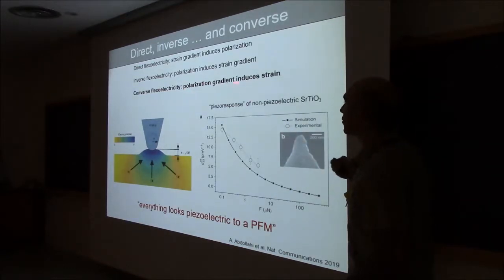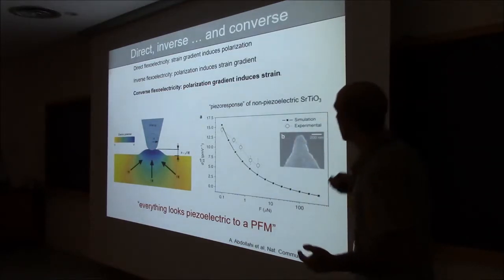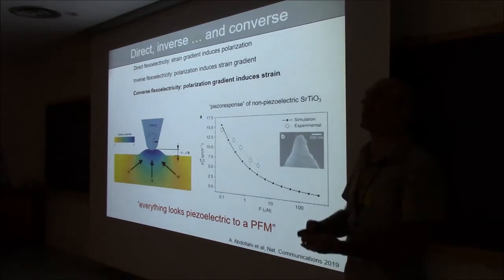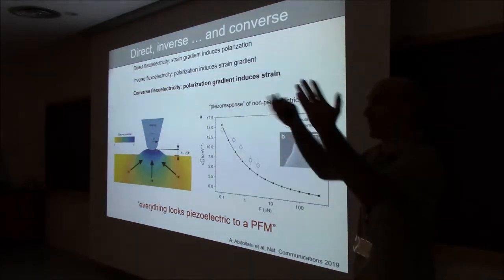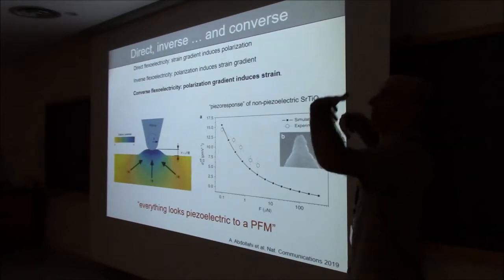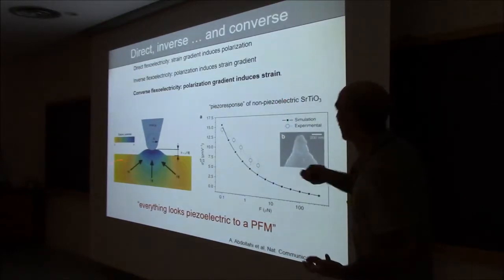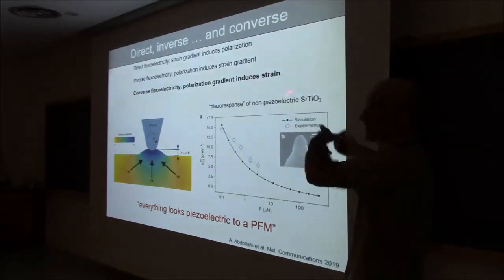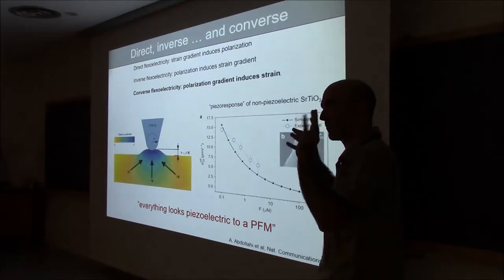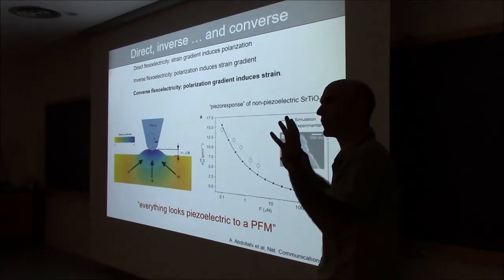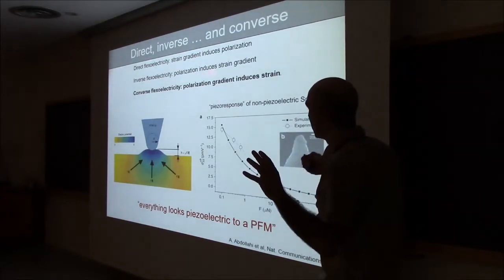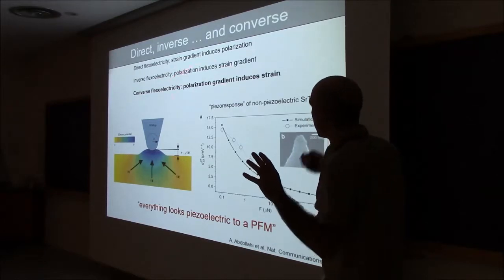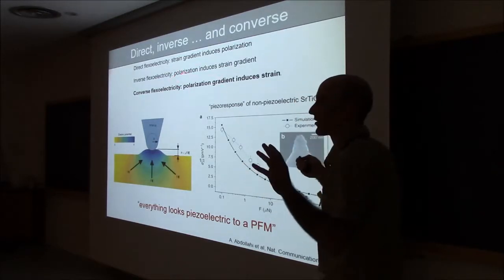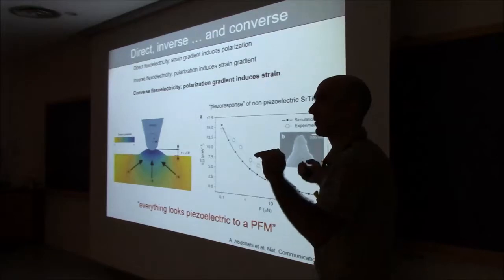Here, the polarization is not homogeneous, the polarization is inhomogeneous, so I have a polarization gradient, and that gives me a linear deformation. Okay, mathematically a linear deformation, but of course, because there's a gradient of polarization gradient, the deformation here is not homogeneous, but hopefully you can see that the physical manifestation is quite different. Okay, so here I have a homogeneous electric field gives me bending. Here I have an inhomogeneous electric field gives me strain.